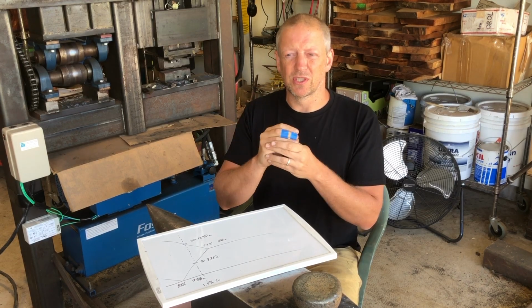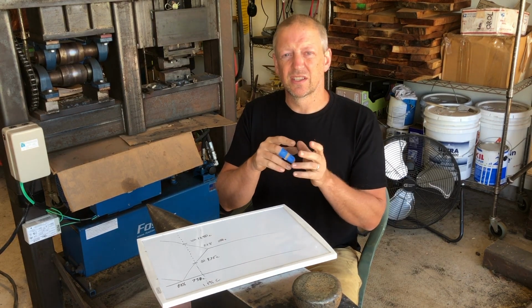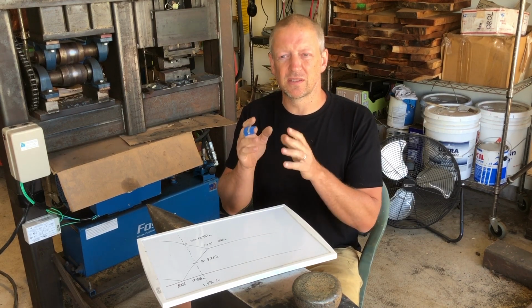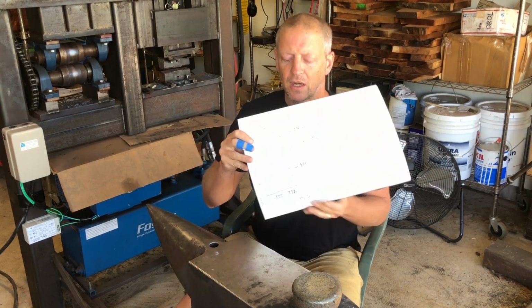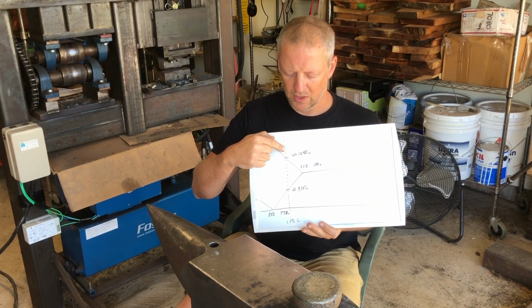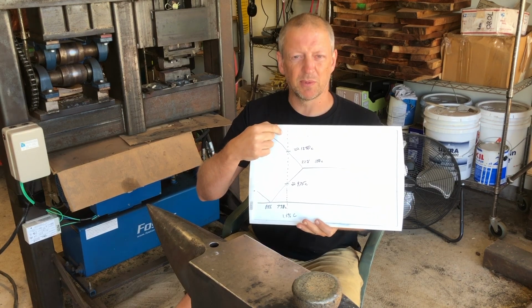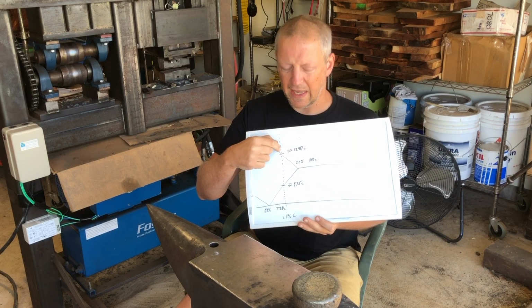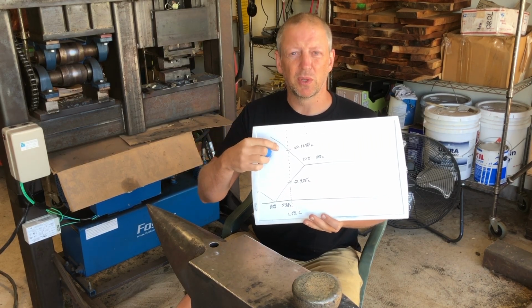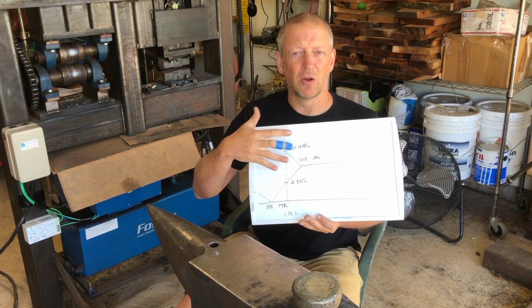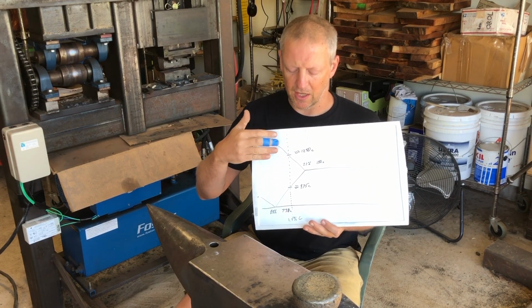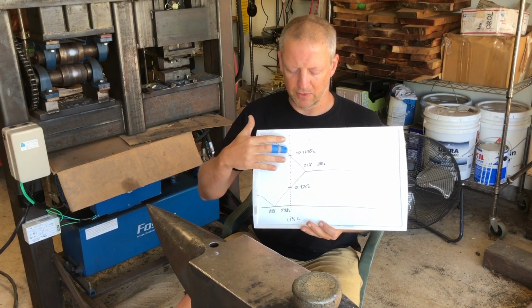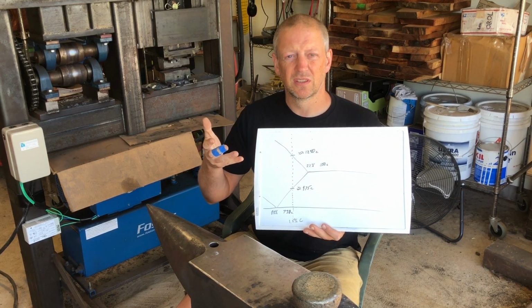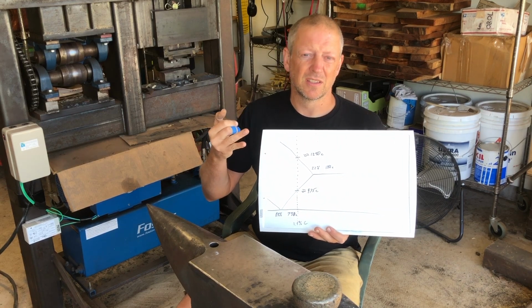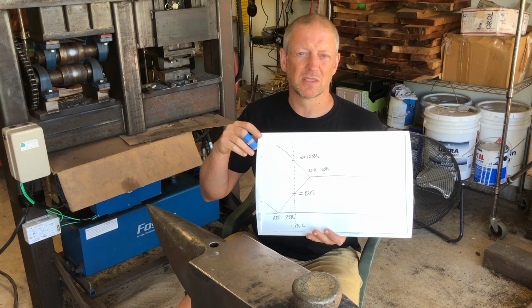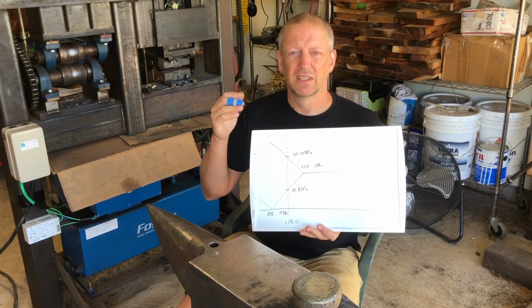Then that dendritic structure that you see in one of the photos, essentially all ingots have that structure at some point during the cooling process. As we are coming down here through, I didn't really draw in the full liquid and then slushy zone, but as we're coming down through the slushy zone, what we get are the dendrites of relatively pure iron, which has a higher solidification temperature, and that is growing into the liquid. And in between those fingers of dendrites, we're trapping liquid. That liquid and the liquid that they're growing into is increased in carbon and, generally speaking, most of the sort of trace elements or third elements you're going to have in your mix.